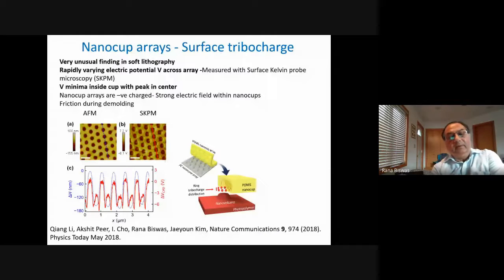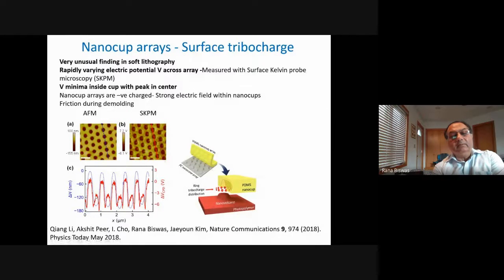And not only does it go through a minimum, but there's also a secondary maximum at the bottom of the nanocup. So it was a very unusual effect that we saw, and we, of course, repeated this on many types of samples, nanocups and later with nanocones, and we confirmed that the surface potential varies rapidly. And the only way this can happen is that the nanocups here have negative charge that you can see schematically over here. And this is caused by the frictional stress during the demolding or peel-off process.